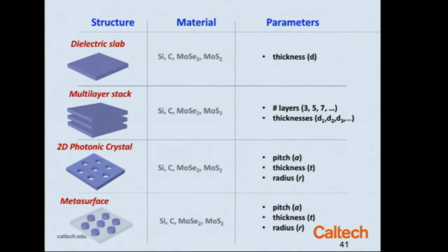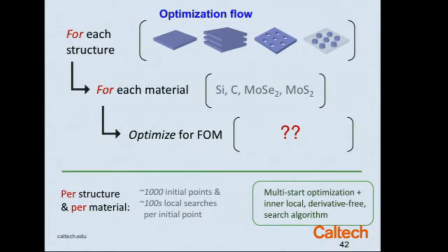And this is a structure that I talked to you about yesterday with arrays of antennas, in this case not metallic, because we need low absorption. These are dielectric antennas. And we've permuted all of these variables, the thickness, the number of layers, the period of these structures, their radius, and their height, with a variety of different materials, silicon, diamond, and these 2 metal chalcogenides. So for each of them, we would like to optimize them relative to some figure of merit. And the question is, what should that figure of merit be?